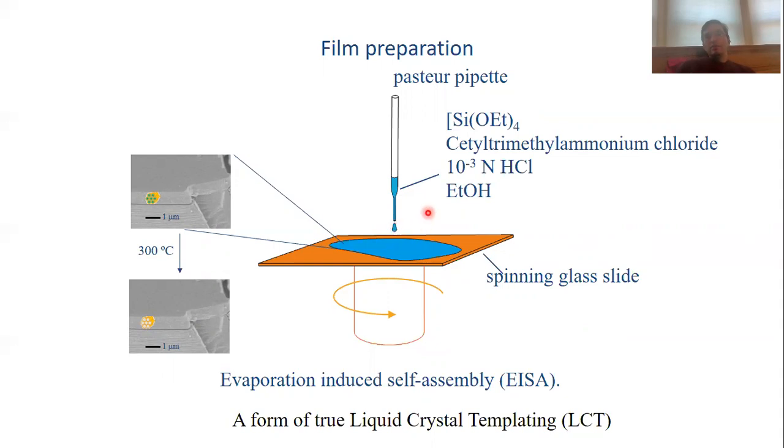And for that reason, the solvent can quickly evaporate. So the ethanol component will evaporate actually quite quickly, and that will lead to an increase of the concentration of the silicic acid, which will now start to polycondense. In a cooperative process, it will again polycondense around the surfactant templates to form a film on your substrate.